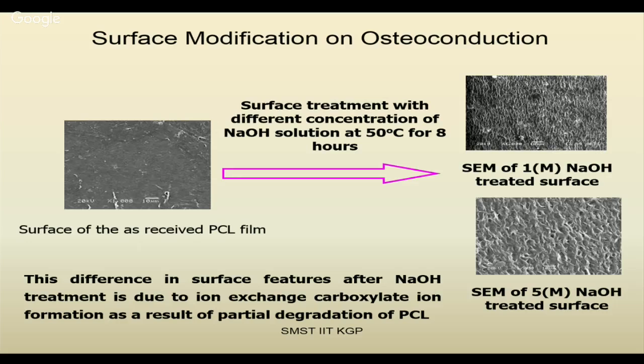So this is one of the studies I think we did back in 2004. This is PCL, polycaprolactone, a polymer, whose surface is smooth, and then once we do some kind of sodium hydroxide treatment, we see that there is a rough surface on the PCL surface.